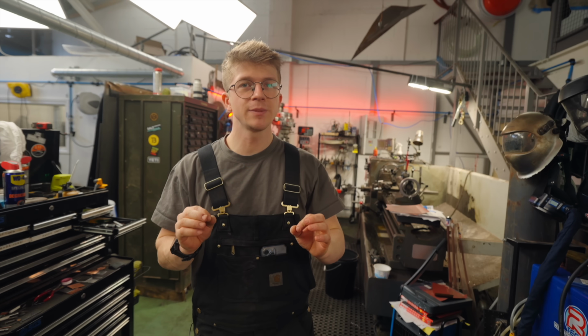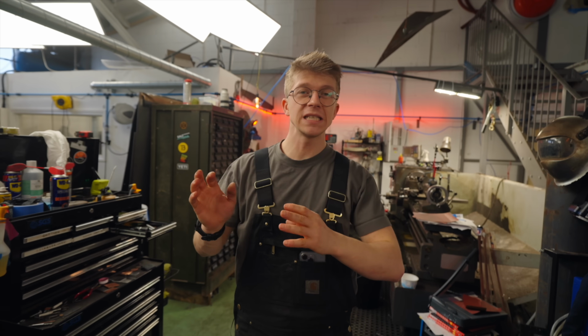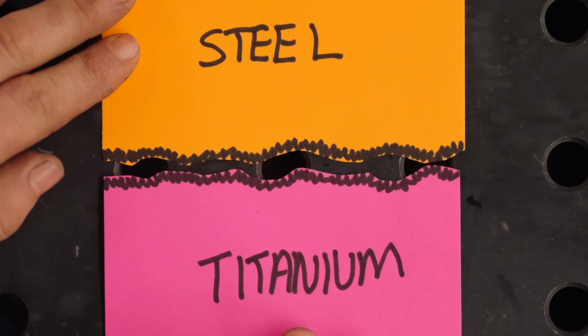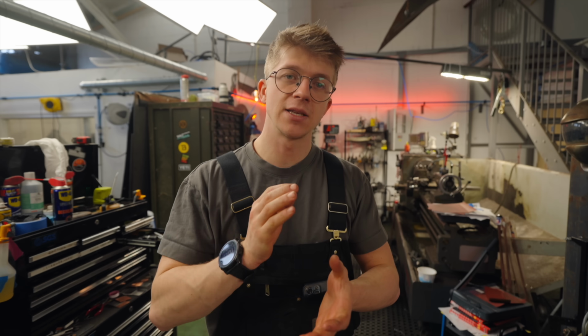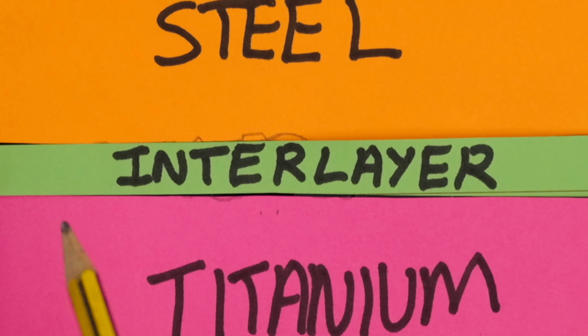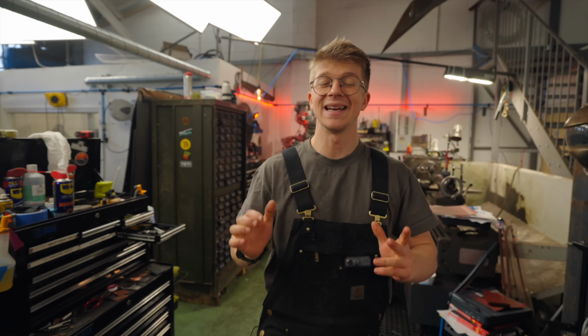For the tiniest little bit of context, if you're new here, welding titanium to steel is very, very difficult because at high temperatures they react and form a very brittle intermetallic compound that is nowhere near strong enough to be at the joint interface. And so what we were doing was experimenting with interlayers between the materials, but in our last episode on the topic, thanks to Dr. Shehzadi's input, we found a new technique to try.